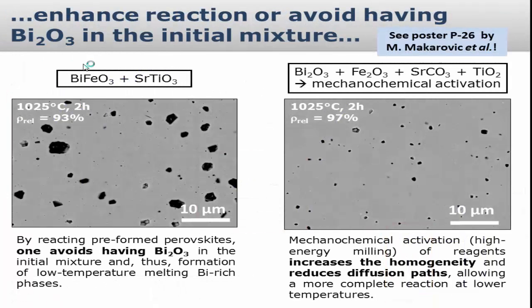How to solve the problem? We thought about two simple things. One thing you can do is to make a more homogeneous, better mixture of the initial components, ideally with very small particle size. These solid-state reactions are basically related to diffusion paths, the diffusion distances. If we have very small particles, this means that the reaction will be completed at a lower temperature.